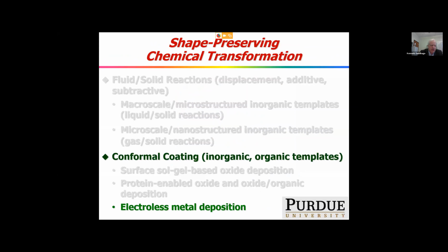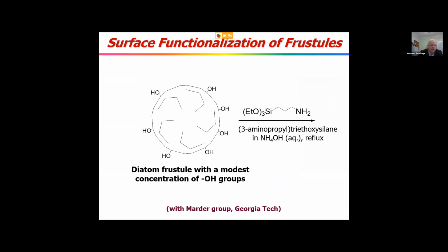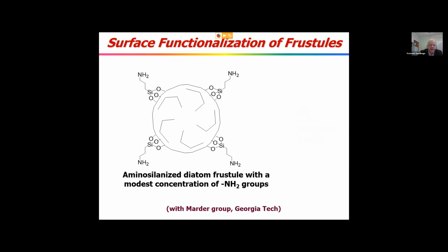Okay, and then very quickly, let me show you how we can make metal replicas as well. Again, we go back to our diatoms, which contain a native amount of hydroxyl groups on the surface. We did this with Seth Marder's group at Georgia Tech. You can take an alkoxide like a 3-aminopropyl triethoxysilane, react it with hydroxyl, and then put amines on the surface, covalently bonded. Those amines can act as sites to bind catalyst particles that will allow for electroless metal deposition.